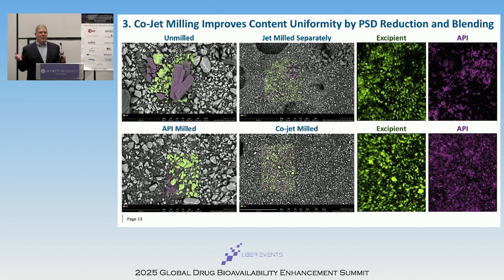If you co-jet mill the materials together, the blending is superior. There's less regions that you see below with the co-jet milled. So it gives a superior blend over just separately jet milling and then mixing.